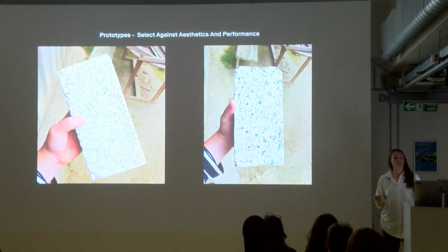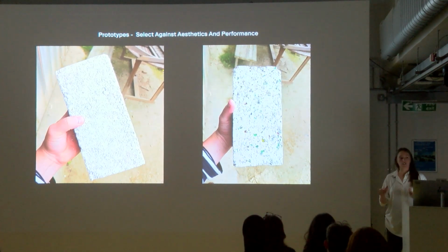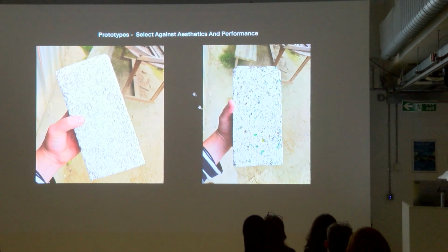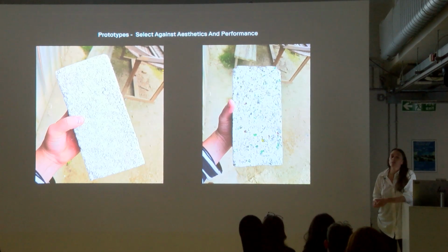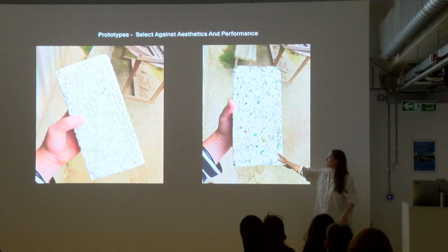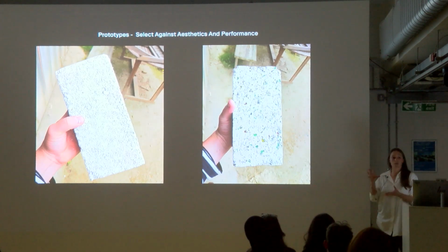Yeah. So the bricks. I'll zoom forward again. There's a comparison. There we go. So the final brick does have glass in it. It's industrial glass, and it's ground in such a way that the smooth surfaces are taken off. This one, you're right, it was in part because of the residual sugars, both from the beer and also from the stickers that you get on your beer bottles. But also you can see that the actual fragments are quite shiny, and because it's so smooth, you end up with nothing that the binder can key into.